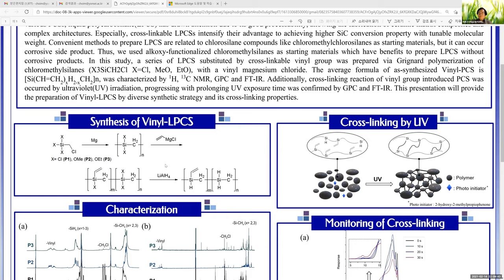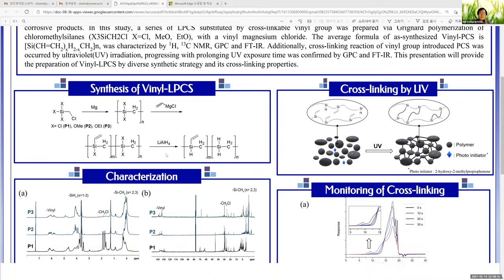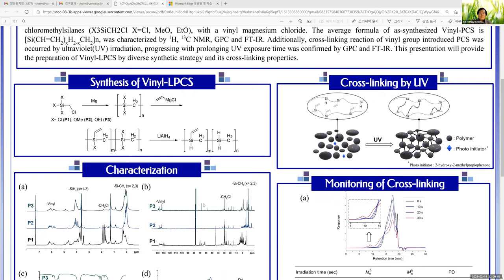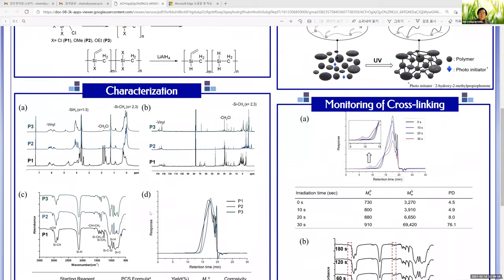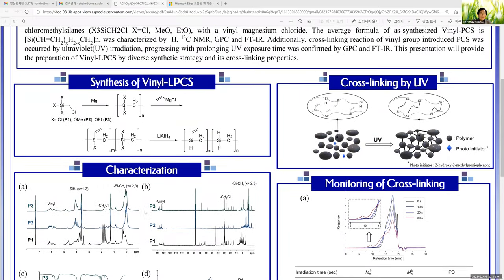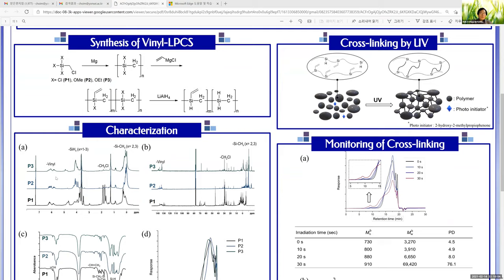The synthesized vinyl polycarbosilanes were characterized by proton NMR, carbon-13 NMR, FTIR, and so on. If you look at the proton NMR here, you can see the very typical vinyl chemical shift around 6 ppm. And also, if you look at the carbon-13, the vinyl carbon showed around 135 ppm.